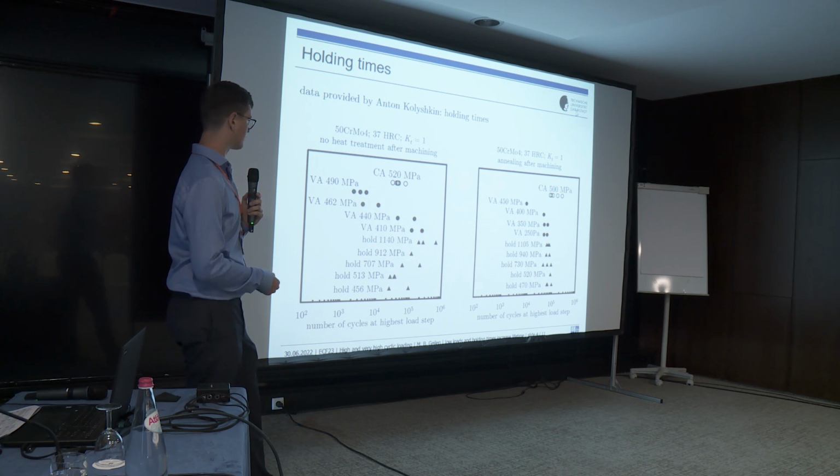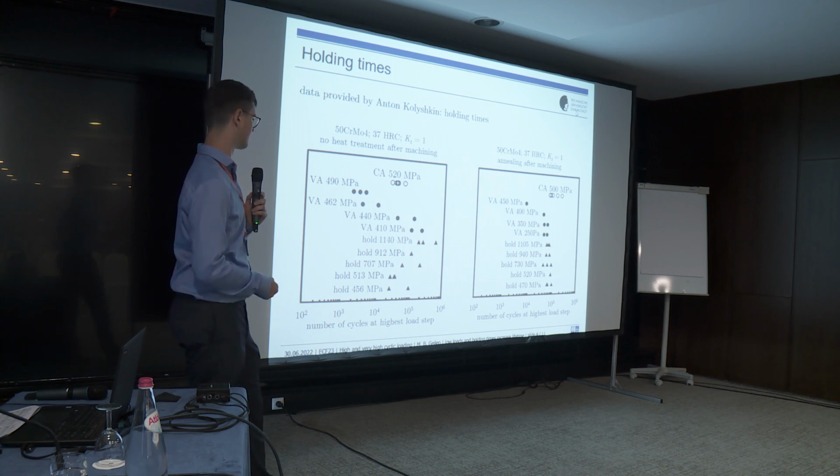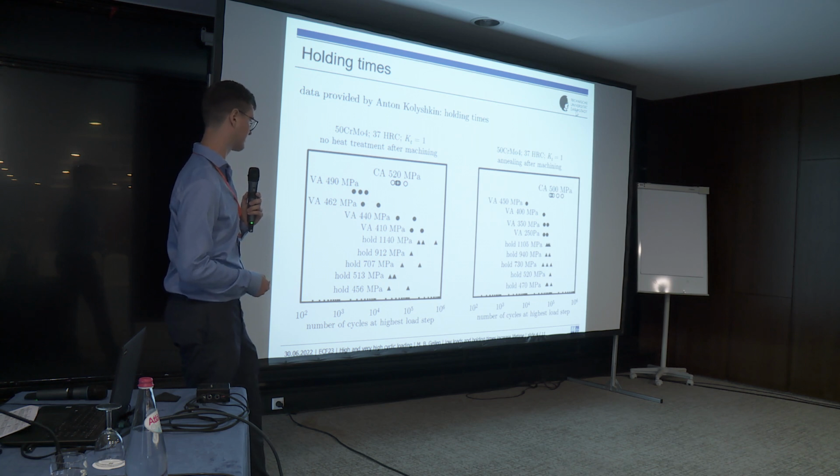And for the lower ones, which were below 90% of the so-called fatigue limit, he did observe somewhat of a lifetime increase. And as we saw for the other ones, he observed a reduction of lifetime.